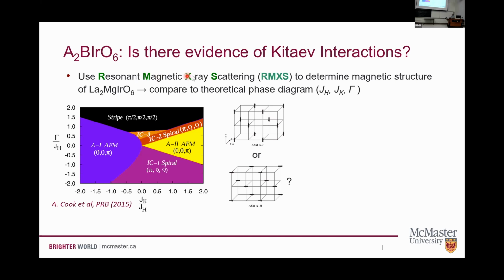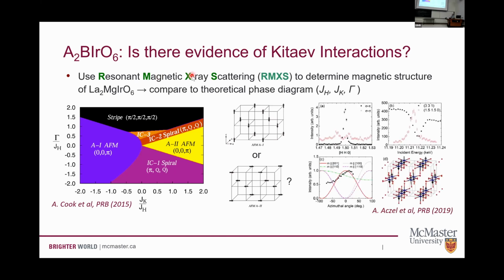So we can use these resonant magnetic X-ray scattering measurements that let us study very small single crystals, because X-rays are very strongly interacting. We can find the magnetically ordered peaks. We can look at the azimuthal dependence of these peaks to pull out the moment direction. That lets us identify the magnetic structure and situate it on this phase diagram.